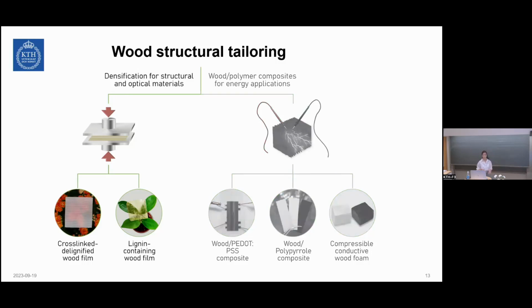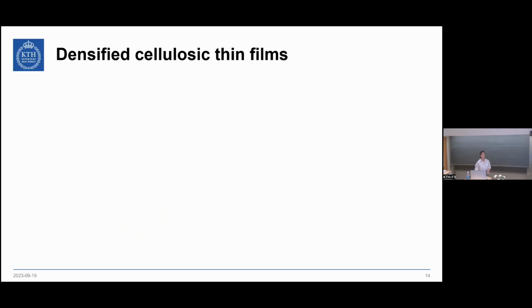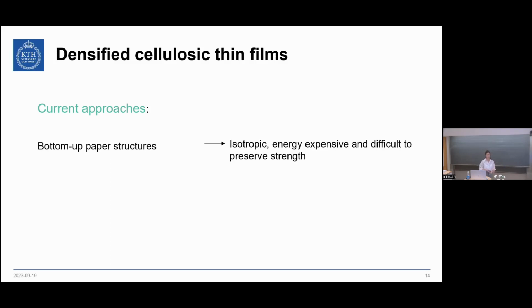So first focusing on the first category. What has been done so far for the purpose of densification is that if we increase the density of the material, we expect the mechanical properties to improve. And the current approaches are mostly of 2 types. Either bottom-up approaches, which means that we first need to liberate fibers or microfibrils from the wood structure, and then build structures that are normally isotropic. However, the liberation of these fibers or microfibrils is energy expensive, and in most cases damages the fibers themselves, which means that in the end we will have materials with less optimal mechanical properties.